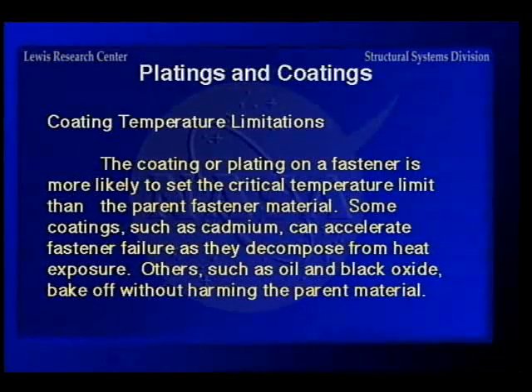Now, on temperature limitations, the coating is more likely to set the temperature limit than the fastener material itself. And some coatings can be a disaster when they decompose, like cadmium. You get hydrogen embrittlement from the decomposition of cadmium. And others, like the good old familiar black oxide, bake off without doing you any harm.